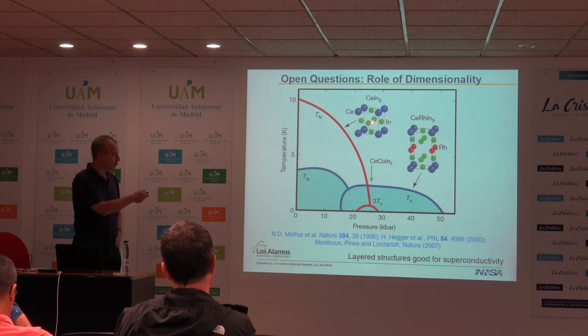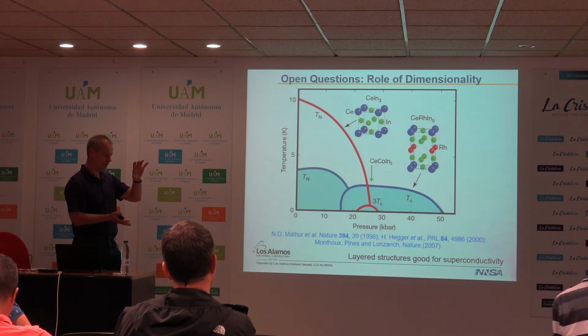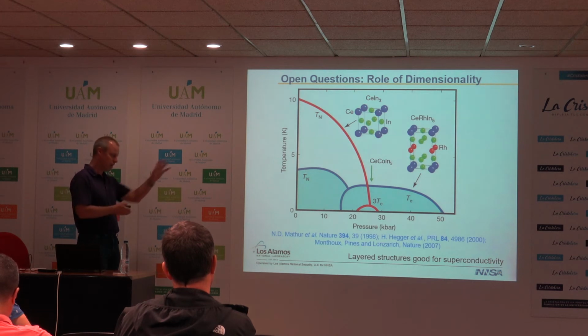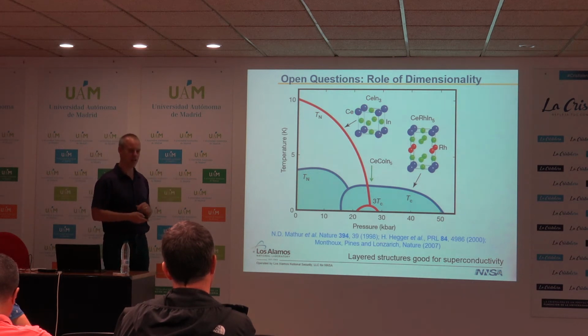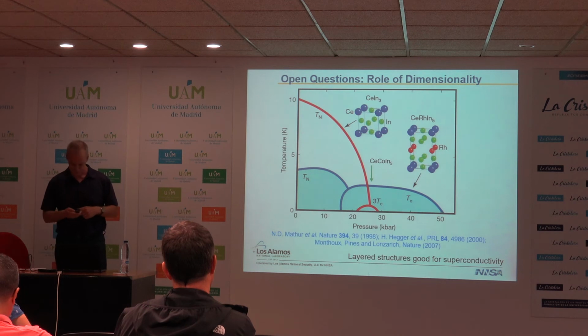But he's also looked at how the superconductivity in cerium cobalt indium 5 evolves as you reduce the dimensionality. So as you go to a single layer of cerium cobalt indium 5 buffered by non-magnetic layers, you can see how TC is suppressed and all these sorts of things. So that's a very interesting direction. I don't have it here, but thank you for bringing it up.